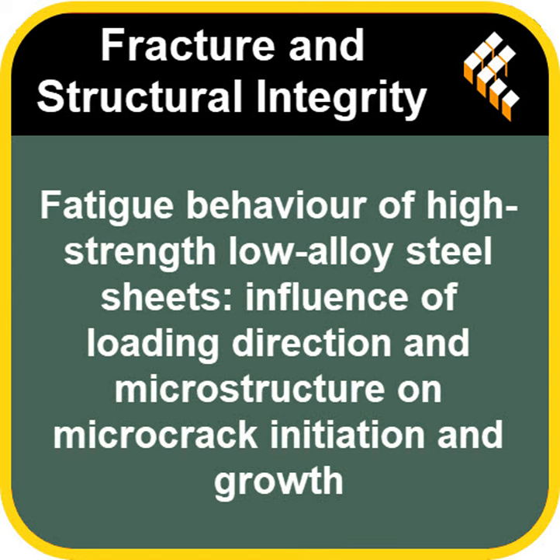And what happened at higher strains, say 0.3%? At higher strains, RD still showed more cracks staying small, trapped within grains, and it had a sort of mixed failure mode, cracks going through grains and along boundaries. But in the TD samples at high strain, the cracks overwhelmingly followed the grain boundaries, a much clearer intergranular fracture mode. And this is where those aligned subgrains seem to provide easy paths for the cracks to run along.